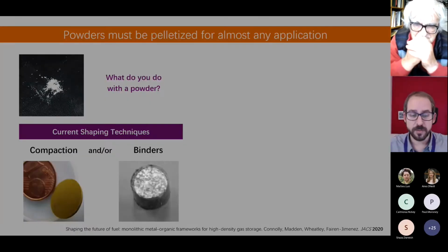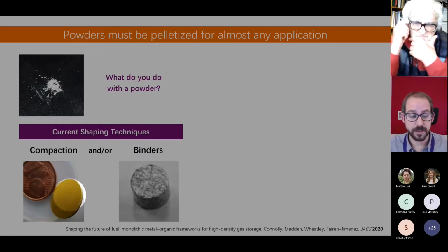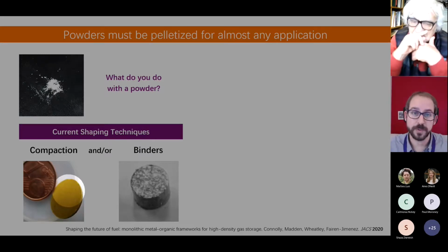We can also use a binder to be able to not use so high pressure. This works really well, but the problem is that we cannot densify the materials too much. If we try to apply very high pressures and densify the materials, we go back to the previous problem, we collapse part of the porosity.